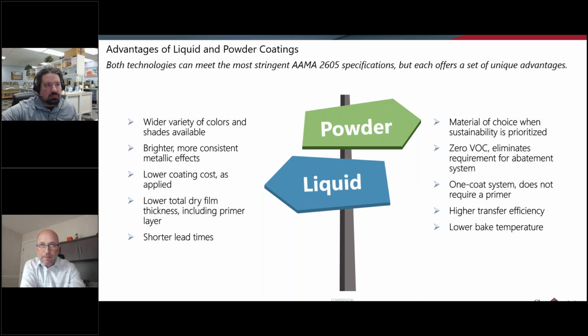When I'm talking about an abatement system, it's this: when you're applying solvent-borne coatings, you can't let all of the solvent evaporate and go into the environment. What you do is you buy an abatement system that essentially burns that material, and usually, well, I think always, uses the heat for something else, either to heat up ovens or to heat the facility. Anyway, that's a good way of utilizing those VOCs that have to be evaporated anyway, but it's also expensive. So liquid coating plants are generally more expensive to install than powder coatings, and a large part of it is because you need an abatement system.